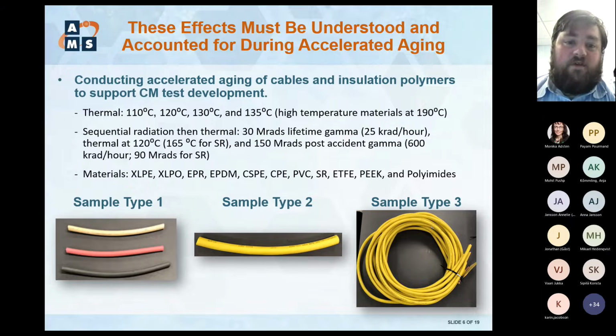And what we'll do is remove the jacket at different points in the aging process. We'll take these out, we'll cut the jacket off to remove the different filler components in the cable, and then test the insulation. These are capped with silicone rubber caps to help prevent oxidation at the ends of the cables, but we do try to sample toward the middle, away from the edges. The reason we're doing these is we're trying to relate the type 1s to the type 3s, which are longer, 25 feet or more of cables. We're doing things like reflectometry and dielectric spectroscopy on those to assess in situ electrical techniques and how effective they are. So we're trying to relate type 1, type 2, and type 3 materials to each other, and based on the data we've gotten, they're each going to show different aging effects and mechanisms. We're really trying to understand the differences we see there.